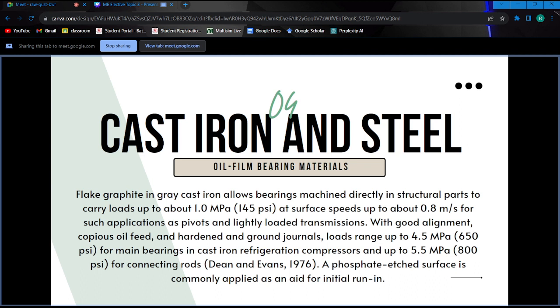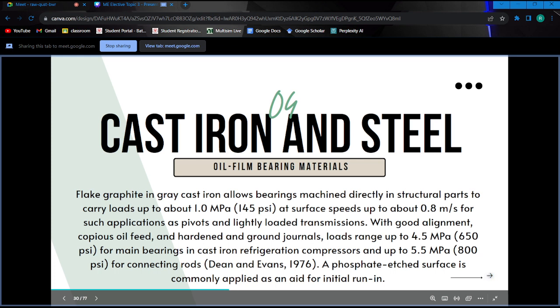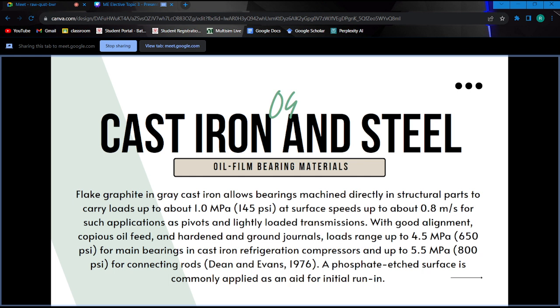Good morning po. For the next oil film bearing materials, we have cast iron and steel. According to Dean and Evans, flake graphite in gray cast iron allows bearings machined directly in structural parts to carry loads up to about 1 megapascal or 145 psi at surface speeds up to about 0.8 meter per second. For such applications as pivots and lightly loaded transmissions, with good alignment, copious oil feed, and hardened and ground journals, the load range is up to 4.5 megapascal or 650 psi for main bearings in cast iron refrigeration compressors and up to 5.5 megapascal or 800 psi for connecting rods. A phosphate etched surface is commonly applied as an aid for initial run-in.